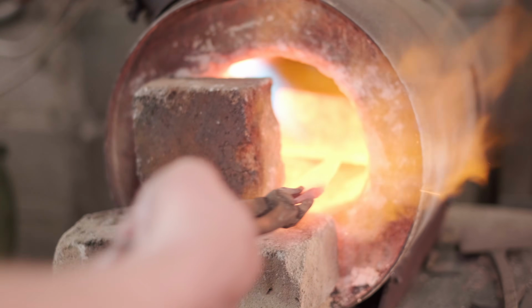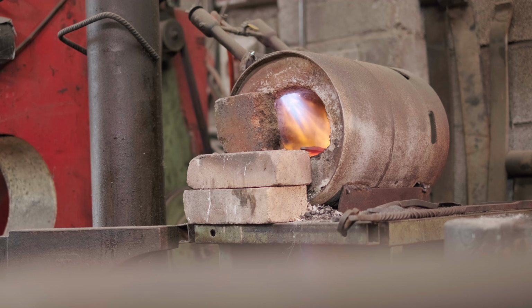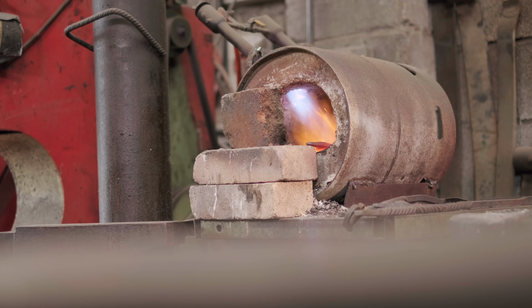And what do we use? Well, a reducing atmosphere is not going to oxidize the surface of your steel. A neutral atmosphere means you've got exactly the right ratio of gas and air going in. You're going to get a good lot of heat out of it, because you're burning all the gas. There shouldn't be any oxygen left over, but to control it exactly on neutral, you actually need equipment in there which is going to measure the oxygen content of your outflow gases and then control the amount of air that you allow in. It's not something the average hobbyist is going to do.